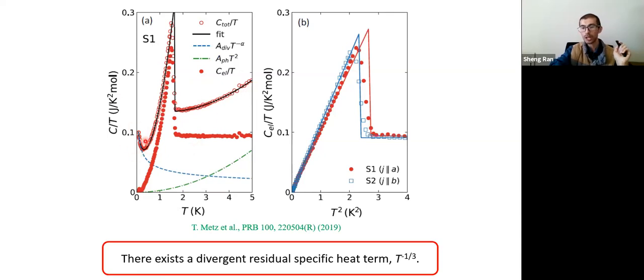And this upturn we checked, very likely it's not from a nuclear Schottky. So we checked, we used a tellurium isotope, and with a different isotope, you still get the same effect. So likely this is not from a nuclear Schottky. But nevertheless, if we took off this upturn, if we subtract this upturn, then of course C over T will go to 0. You subtract, you take off the divergent part, but also the entropy is now conserved.